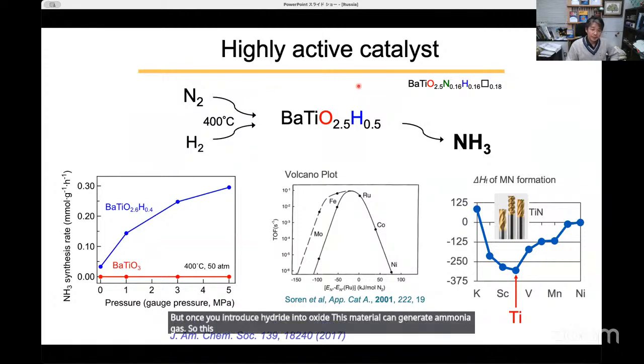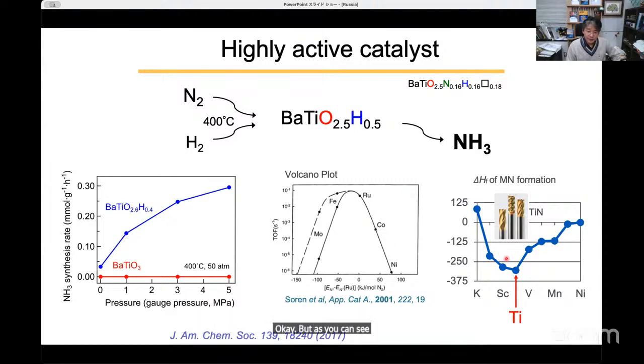But once you introduce hydride into oxide, this material can generate ammonia gas. So this is a nice catalytic material. The amazing thing is that titanium is not regarded as a good catalyst for ammonia synthesis because of the very, very high formation enthalpy for titanium nitride. Titanium nitride is very famous as a coating for devices, with a melting temperature of more than 2000 degrees C. So in this regard, titanium is not active for ammonia.